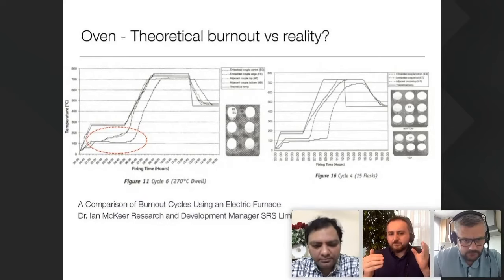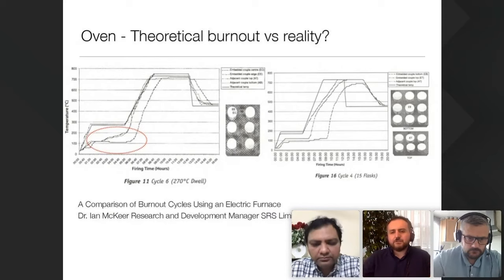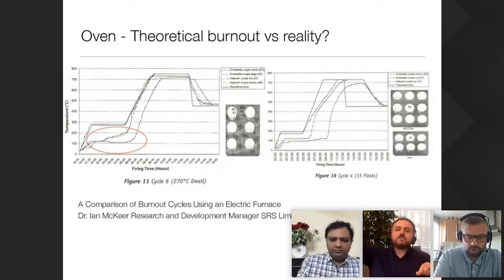That water boils at 100 degrees, right? And while it's boiling, until the whole water has been removed, the temperature inside the flask cannot go above, let's say, 120 degrees - it's very, very difficult. So there is this lag between what you think will happen to your burnout and what really happens, because of the boiling of the water, you have this step where you stay at the 100 degrees Celsius elements. Once all the water is gone, then you increase.